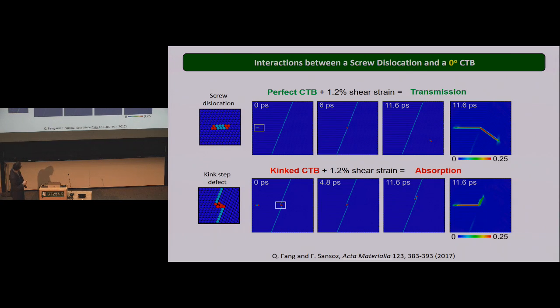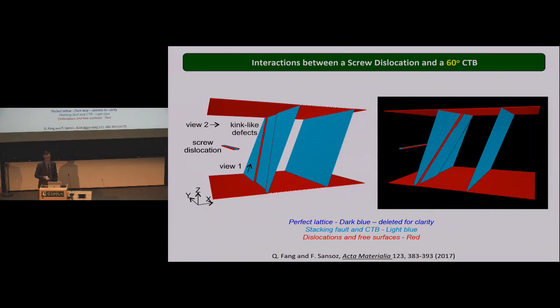And what it shows is the defect will totally absorb that dislocation and now form three dislocations that cross-slip along the twin plane. And so it's an absorption mechanism versus a transmission. And in terms of mechanical property and especially ductility, this produces very different results, all right? Just by using one defect in the simulation. And we look at different cases.